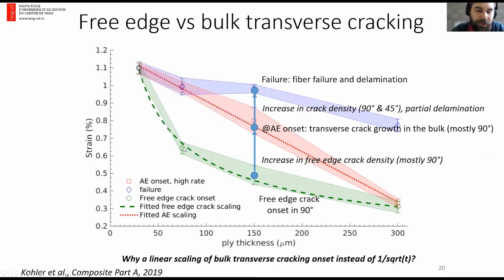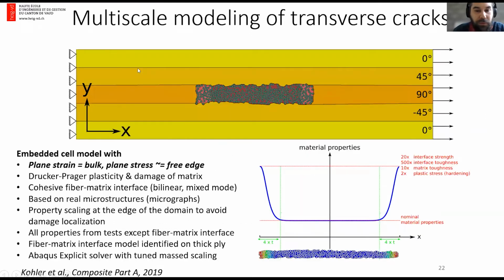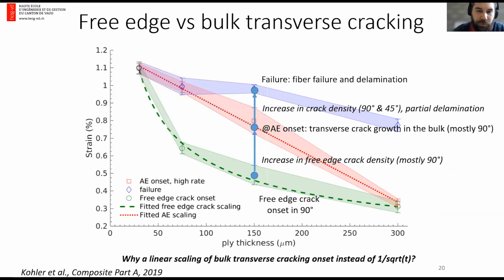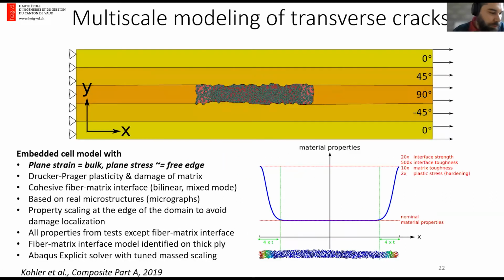By decreasing the ply thickness, we not only shift the onset of free edge crack appearance, but also we shift the onset of propagation of these transverse cracks in the bulk of the laminate. And finally, for the thinnest ply, we couldn't even observe free edge cracks before the final failure of the laminate. So this is very interesting, but this difference between the free edge and bulk behavior is a bit difficult to understand. So what we did to try to analyze this is to model